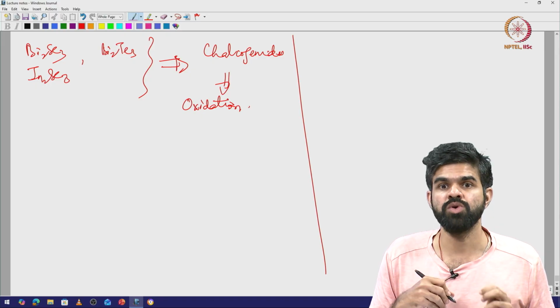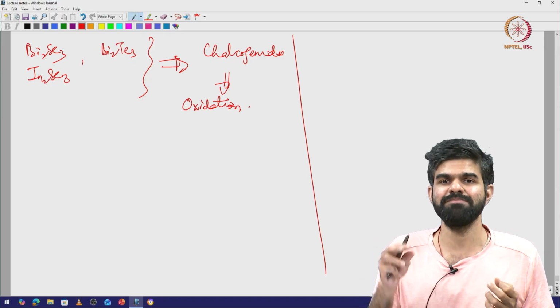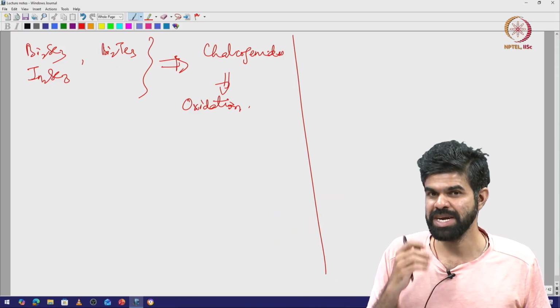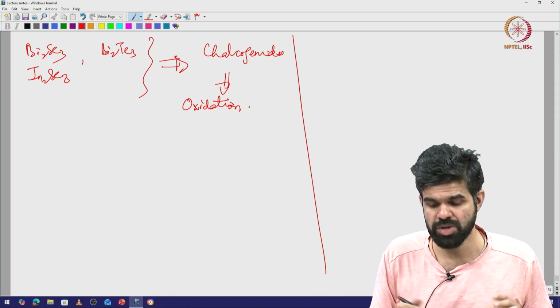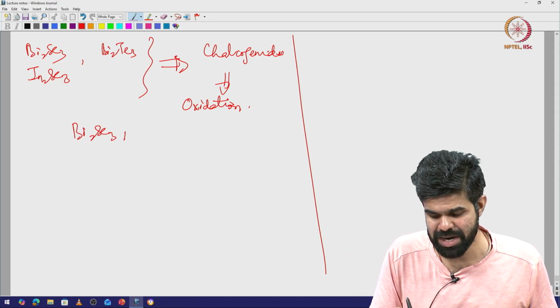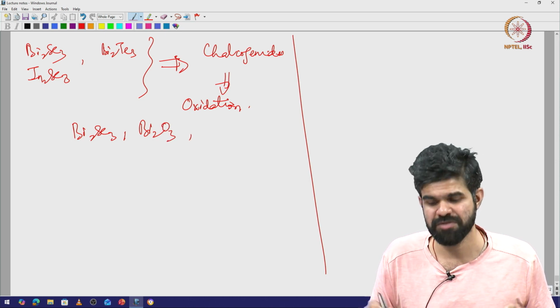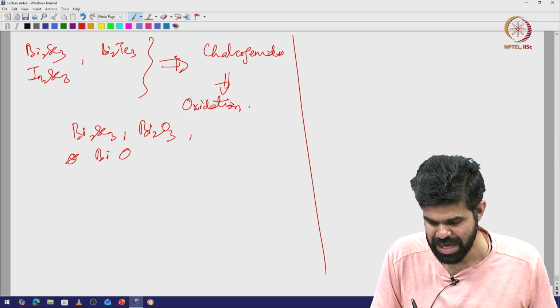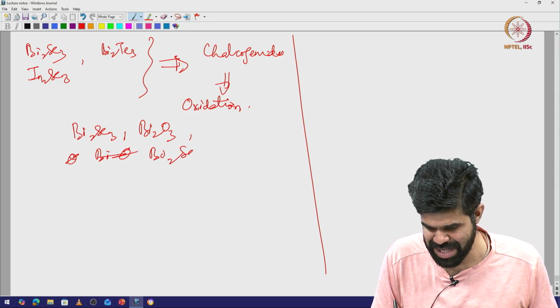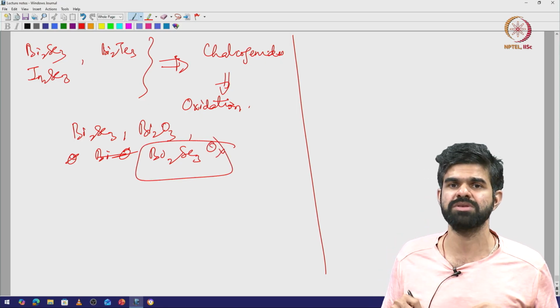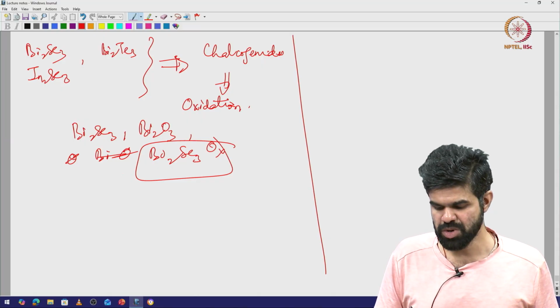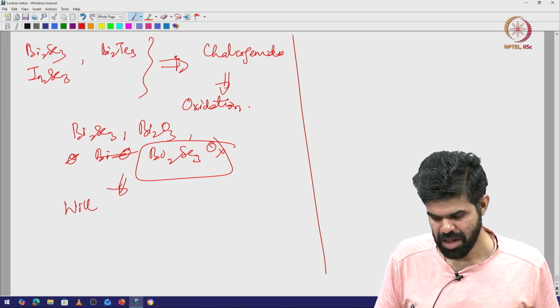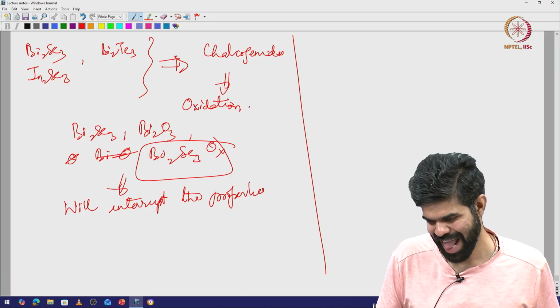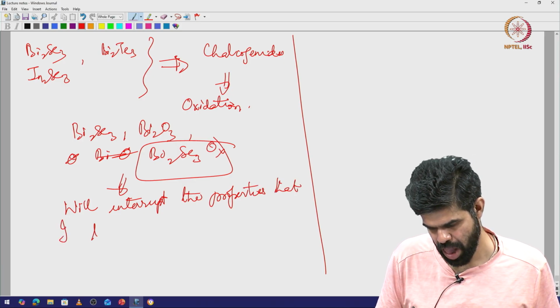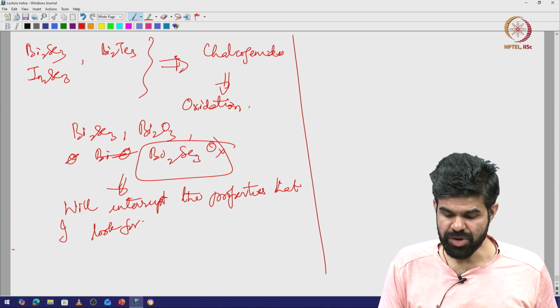So when I wanted to grow bismuth selenide, but I did not make sure that I have removed all the oxygen from the system, I still have about 10 power 13 oxygen molecules, and so I end up getting partly bismuth selenide, partly bismuth oxide, a combination of everything, or some oxidized phase like Bi2Se3Ox, some bismuth oxyselenide or something like that. This is going to affect my properties. This will interrupt the properties that I am going to look for. As a result, you need to pump down more.